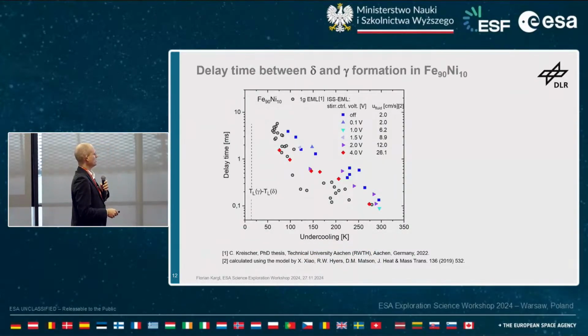So you can have a look at the delay time as a function of undercooling. So there's this time lag between growth of the metastable and the stable phase. And you can plot this as a function of undercooling. And again, for different experiments with strong stirring, with slow stirring here and intermediate stirring, what you're able to do on the station effectively in microgravity conditions. And you see, well, that's the 1G EML ground data, strong stirring, and the delay time for a particular undercooling gets longer when you have no stirring. So clearly the fluid flow has an impact also on when the stable phase nucleates in the metastable phase and starts to grow. So this is work in progress. There are currently models that are developed to describe this delay time as a function of undercooling. There is a description already, I would say 2 models that are competing at the moment. And the second point is then to include this fluid flow topic as well.